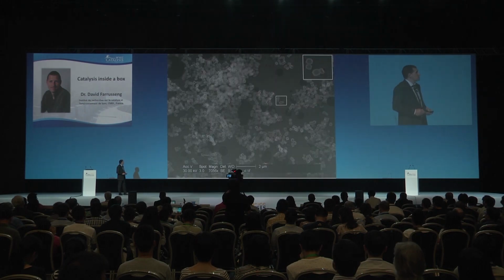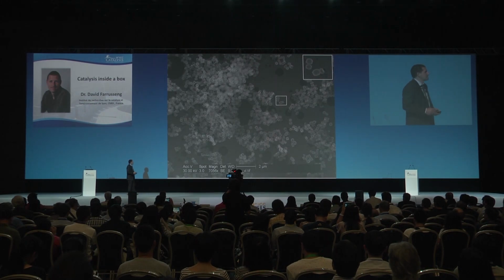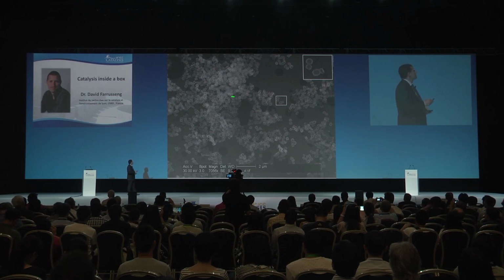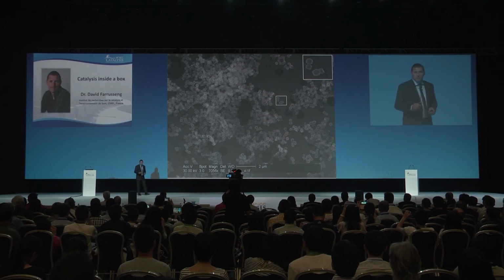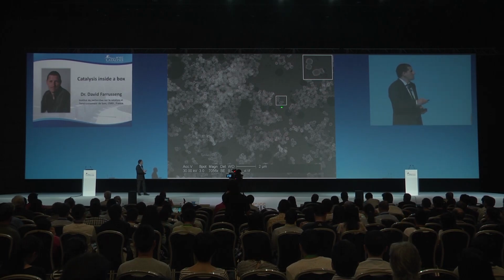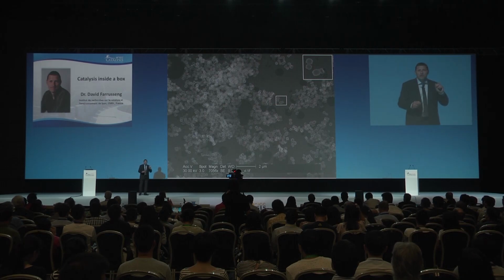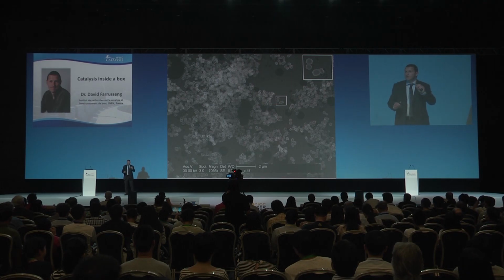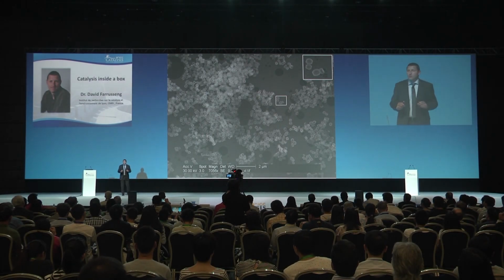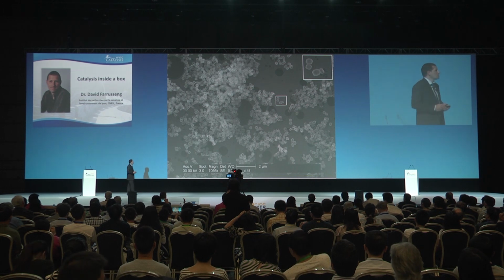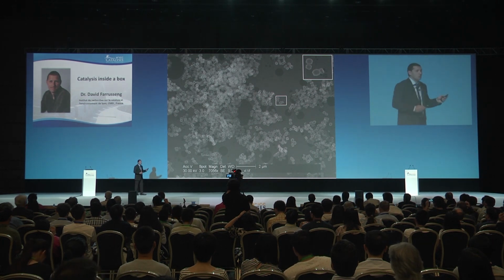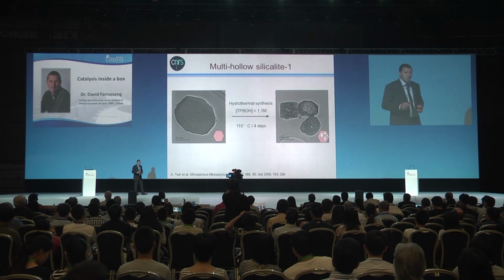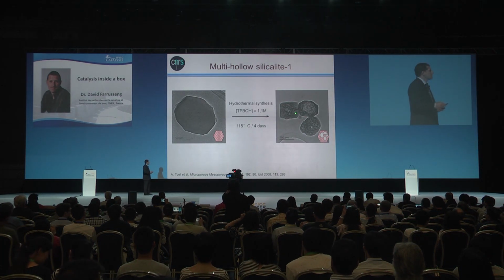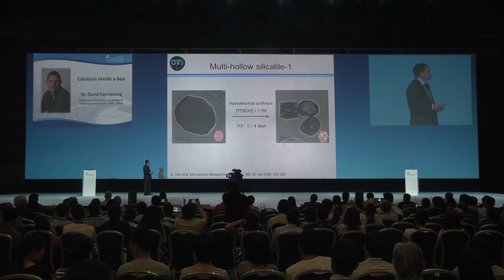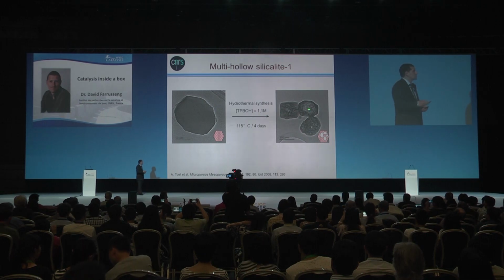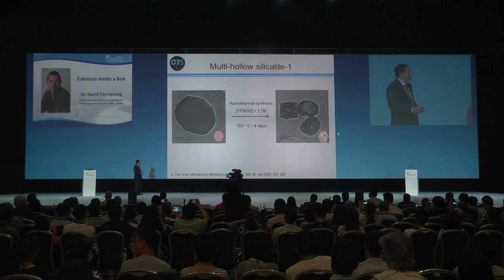And you can see here on these STEM pictures that all the crystals have the same size and all are hollow. It is very important to see the homogeneity. They have all the same cavity volume, which will be used in the next slides as nanovessels, as nanoreactors to control the size and composition of the nanoparticles. So all the same size, all the same cavity volume. It is also possible with variations of the template to make not only a large cavity, but smaller cavities which are interconnected to each other, like this here, if you want to see the scheme.